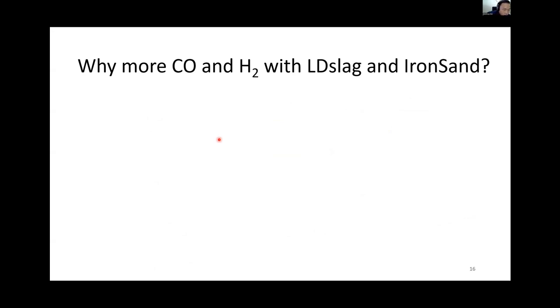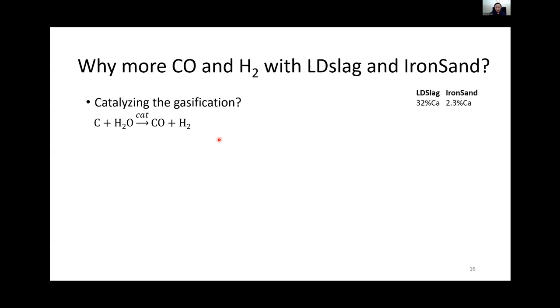One question may pop up: we found the CO and hydrogen is higher when we use LD slag and iron sand, and I want to know why this happens. One explanation could be the calcium's catalysis on gasification. LD slag and iron sand have a significant amount of calcium. And actually, the LD slag particle is easy to break down, either in cold condition or hot condition. We find a lot of fines when we operate with LD slag.